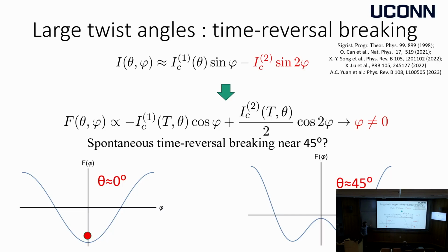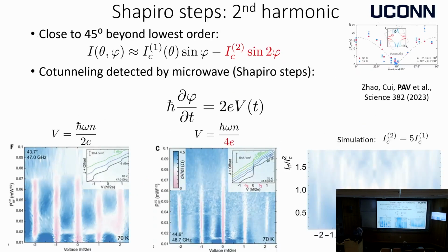So there are two ways you can convince yourself, two steps. So first step, you want to convince yourself that the relation between current and phase is exactly doubled with respect to the ordinary case. The way this is done, or at least one way you can do this, is to probe the dynamics of the system. And with the well-known second Josephson relation, basically the time evolution of the phase is related to the energy difference for the Cooper pairs across the interface. And in the ordinary case, one Cooper pair tunnels, so you have 2e here, and you expect a resonance to occur at voltage that is related to the oscillation frequency of the phase.